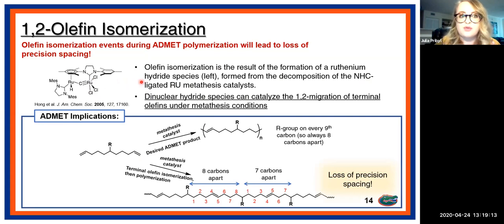So you want to avoid forming this ruthenium hydride species because then, for example, this double bond could be moved to here. And when you incorporate that into the ADMET polymer, what happens is you'll have the desired spacing, in this case where the R groups are 8 carbons apart, but you would then have some incorporation of monomer where the R groups are seven carbon atoms apart. So you'll lose your precision spacing. This is the desired ADMET product where the R group is on every 9th carbon, so 8 carbons apart.